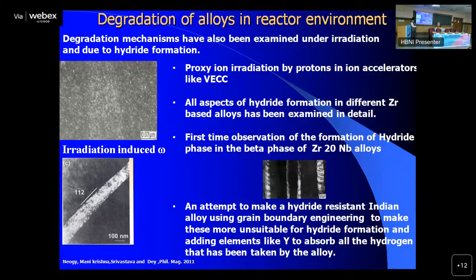But nonetheless we have made one effort where we have tried to develop a hydride resistant alloy, where the grain boundary engineering ensures that the hydrides do not form at the grain boundaries. The hydrides do form at the grain boundaries, and if you engineer the grain boundaries in such a way that you deform them, the texture is suitable and the hydride doesn't form at the grain boundary, it tries to form somewhere else. Now, if you put an absorber or a sink for hydrogen like yttrium, it will draw all the hydrogen in. Hydrides will not form at all. So then it becomes a hydride resistant alloy. So there was a beginning made for developing an alloy which will be hydride resistant, and it has also been published. This work needs to be taken forward further.